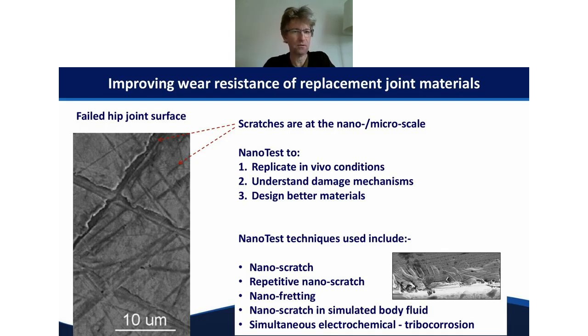deformation. So what we do with the nanotest is we simplify that geometry to look at single asperity contact, just as I described previously, and that allows us to have a better understanding of the stresses involved causing the different deformation. And we can look at the deformation on the surface and convince ourselves that we see the same type of patterns in the scratch test as we do in the retrieved joints. We've got a wide range of different tests. We can do single scratches, we can do repetitive scratch tests, we can do so-called reciprocating or nano-fretting tests. We can do all of those things in simulated body fluid and other liquid environments.